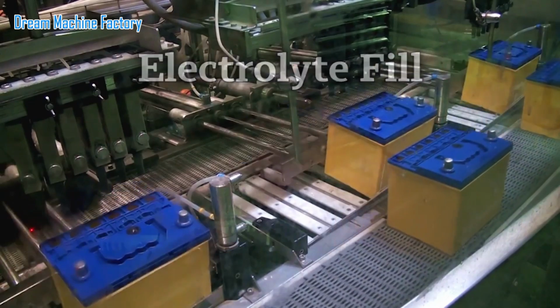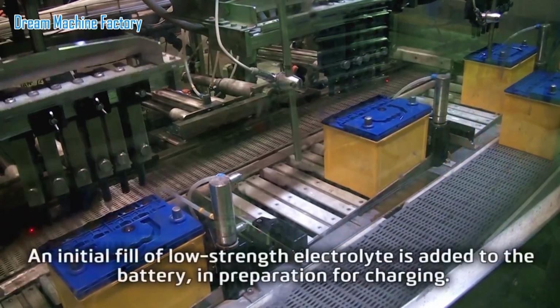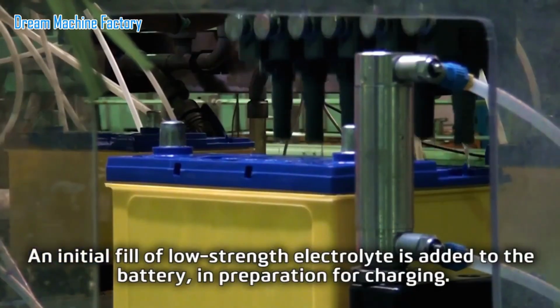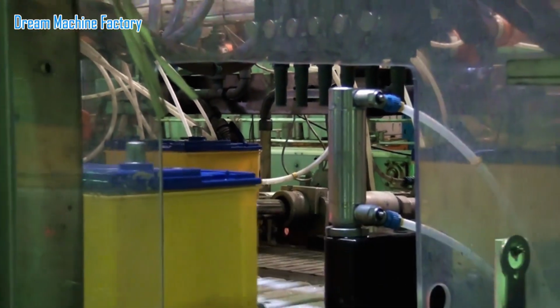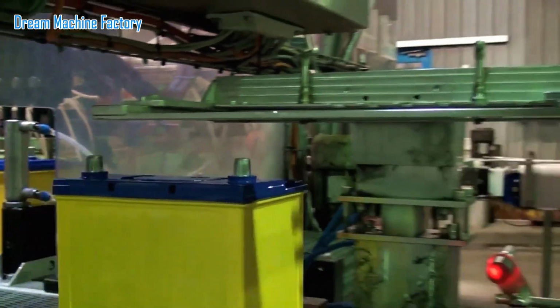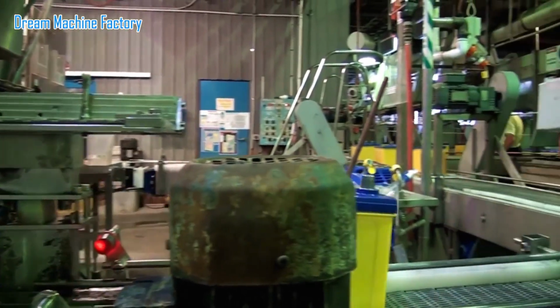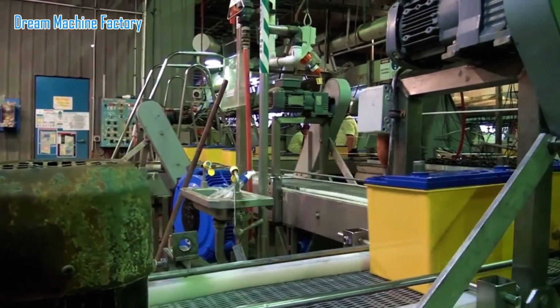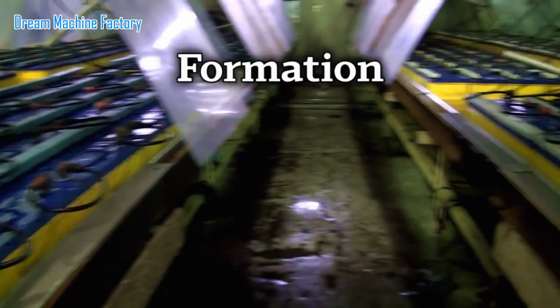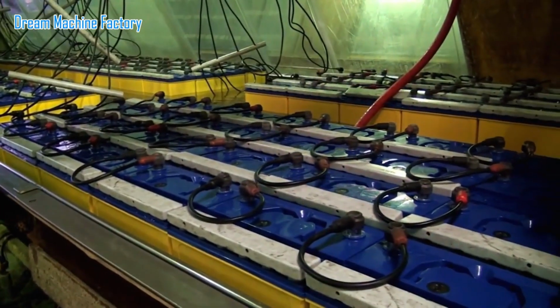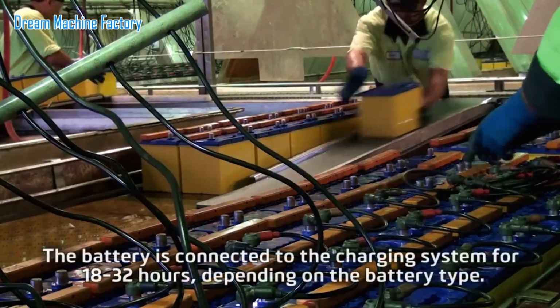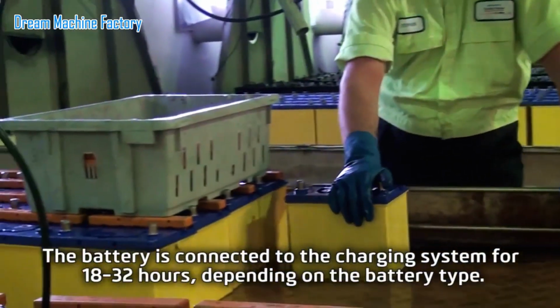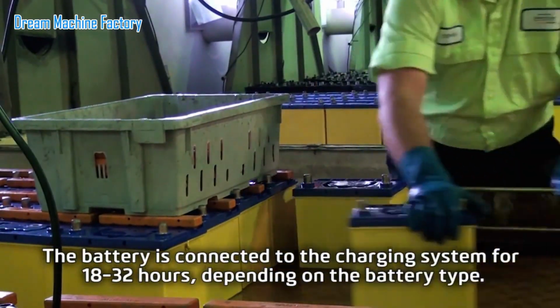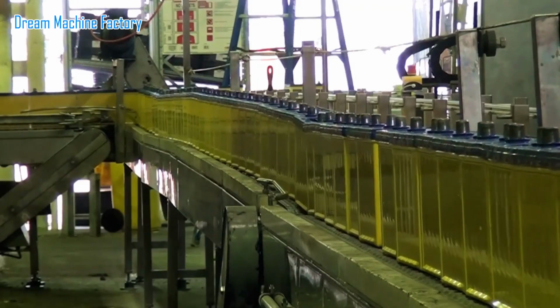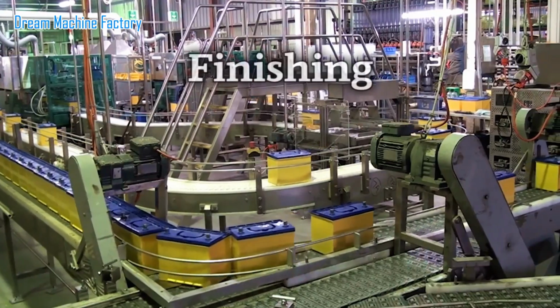In the electrolyte fill stage, a carefully measured amount of low-strength sulfuric acid solution is added to each cell. This activates the chemical components and prepares the battery for its initial charging cycle. During formation, the battery is connected to a controlled charging system for 18 to 32 hours. This process activates the chemical reactions within the plates, forming the active material essential for energy storage.